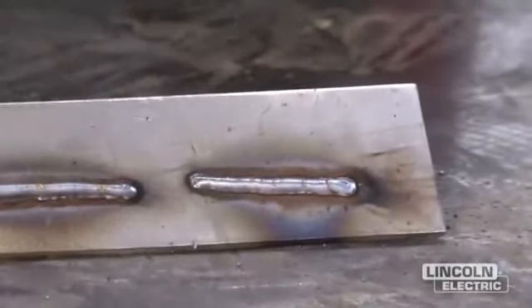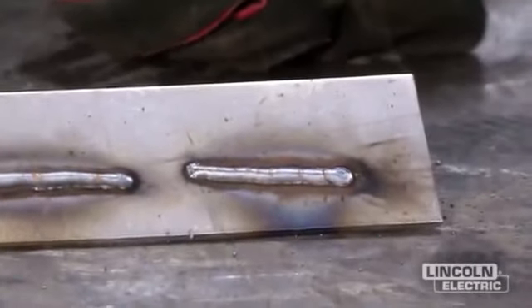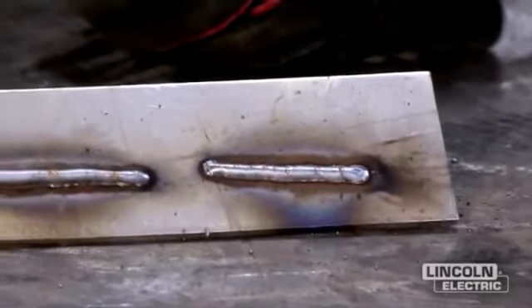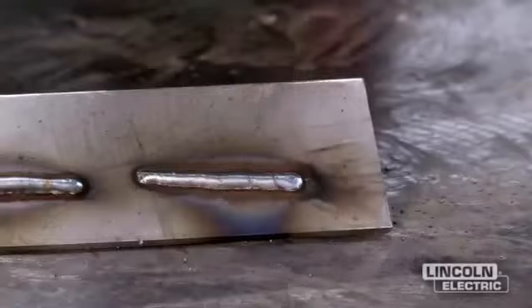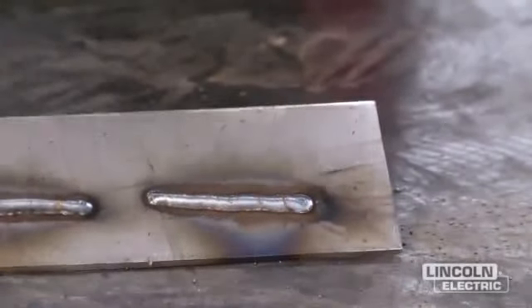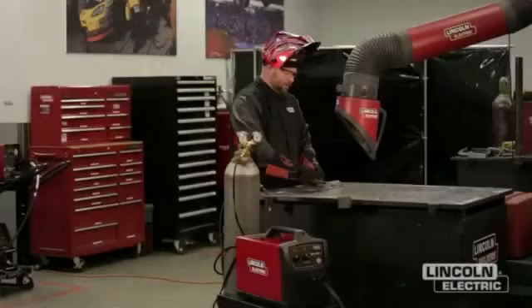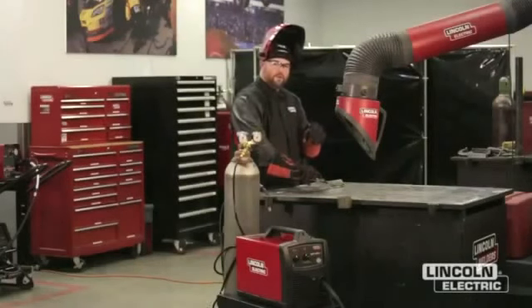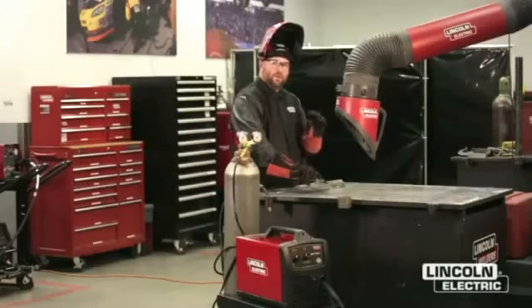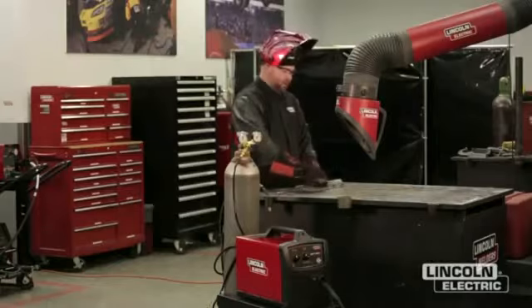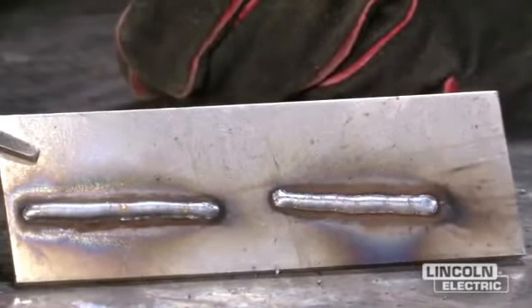And you'll notice the crackling sound. We are using the short arc process for GMAW. So that sound that you hear is the wire shorting to the plate up to 200 times a second. So when you do get the right wire feed speed and voltage, you'll hear a real nice crisp crackle to the arc, and that's what we're going to be looking for here.